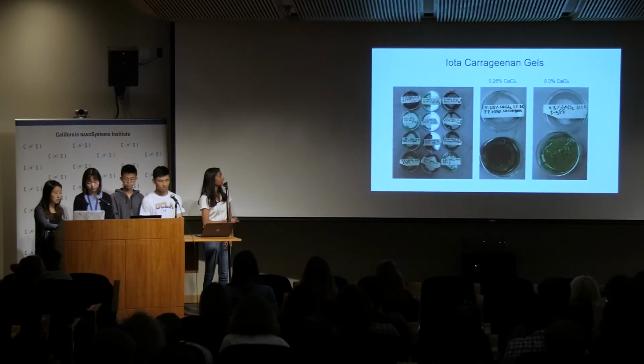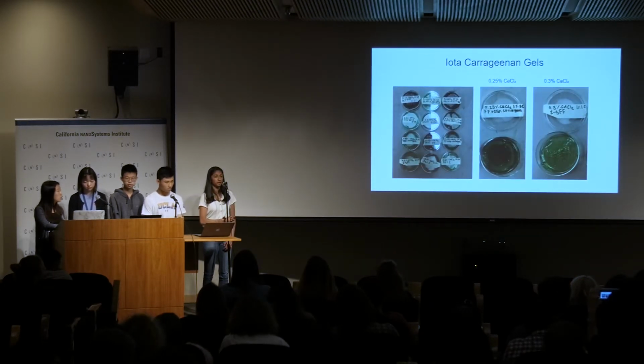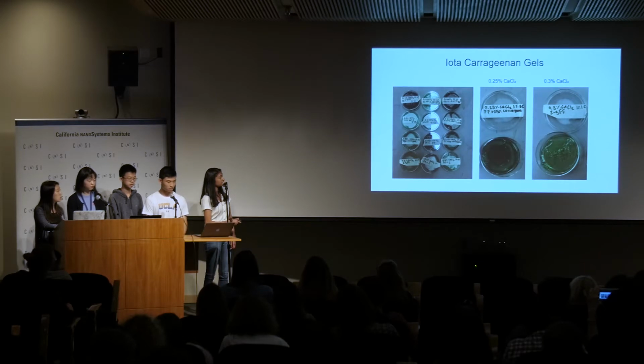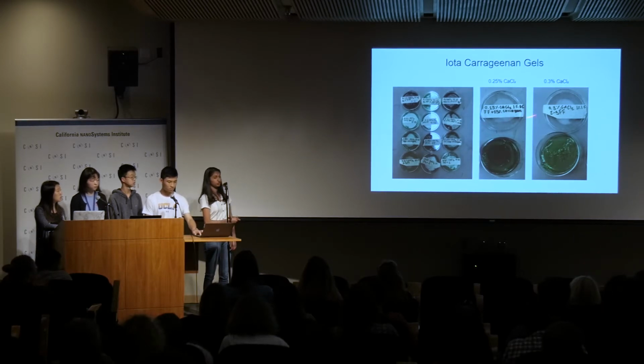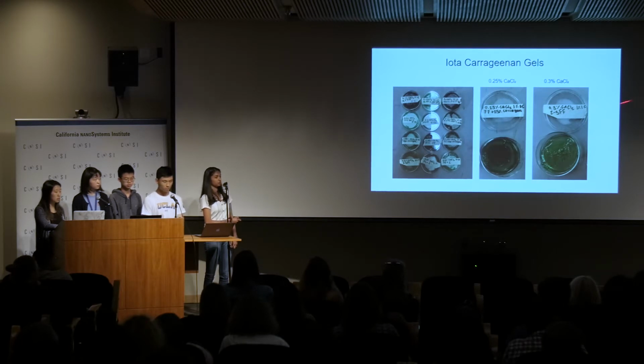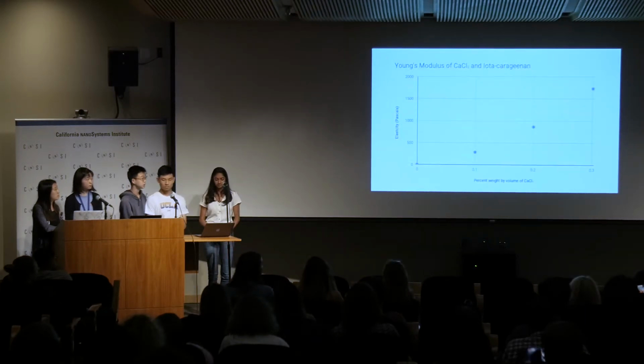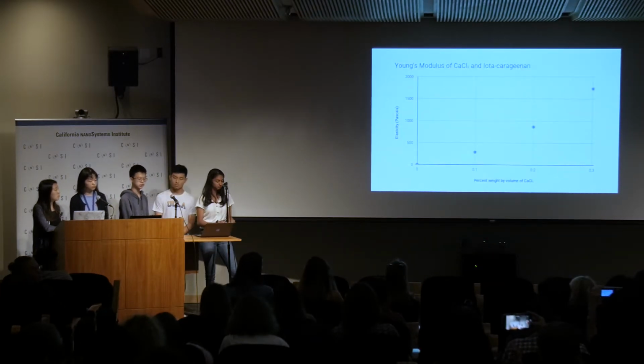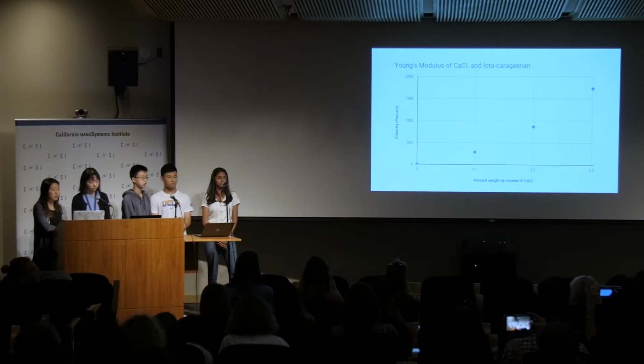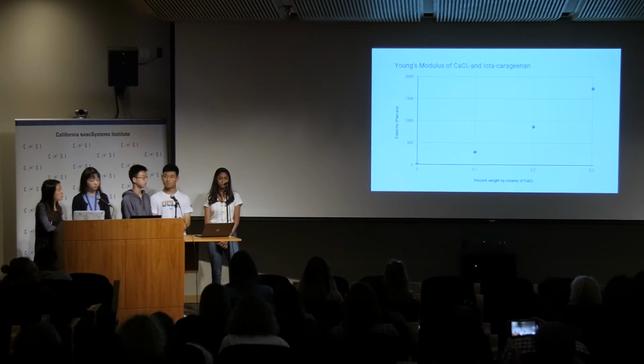So as you can see here, these are all of our gels for iota-carrageenan and CaCl2, and here are the ones. This is the 0.25% of CaCl2, and this is the 0.3% of CaCl2, which we found most ideal. As we tested our Young's modulus, we found the more CaCl2 we put in the gel, the higher the Young's modulus was.